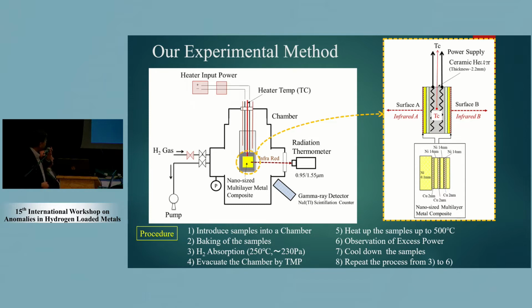At the beginning of the experiment, we introduced the samples into the chamber and baked them to remove impurities, mainly water and carbon. After that, hydrogen gas is filled in the chamber for hydrogen absorption. Then we evacuate the chamber with a turbomolecular pump and simultaneously heat the sample up to 500 degrees centigrade. By doing this, hydrogen atoms absorbed in the nickel bulk are released and diffuse through the multilayer, and then we observe the excess power, anomalous excess heat.